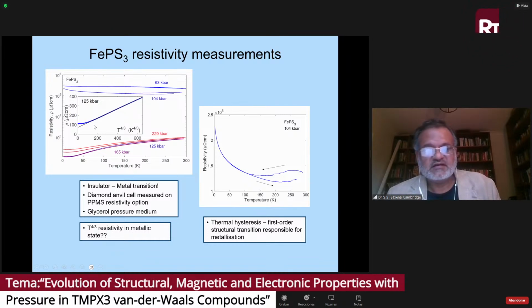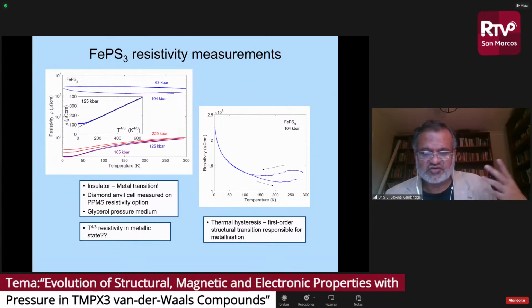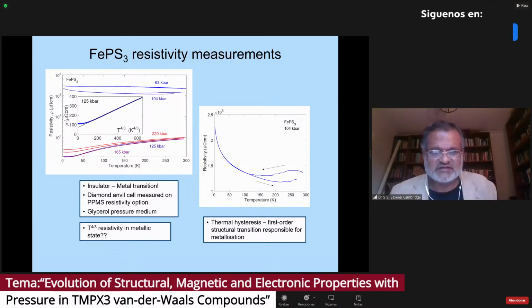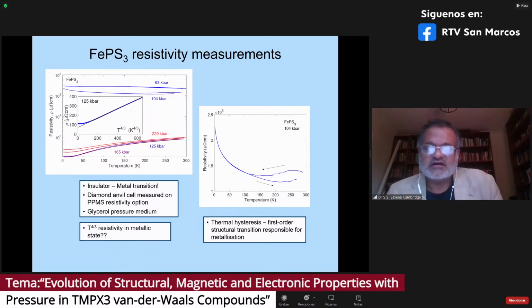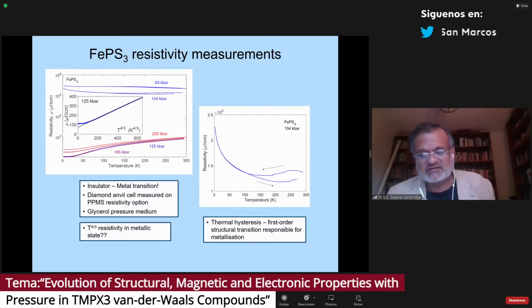We don't know yet. But the initial ideas are that it could be some kind of Kondo coherence setting in, which would be quite unusual in a d-metal system of this type with very light masses. But these are again some evidence, new behavior coming out of, I would say, quite challenging experiments. We're doing 4-point resistivity under fairly hydrostatic conditions.